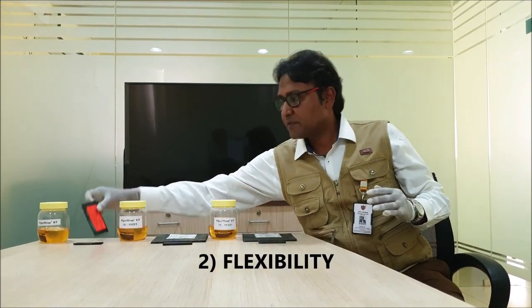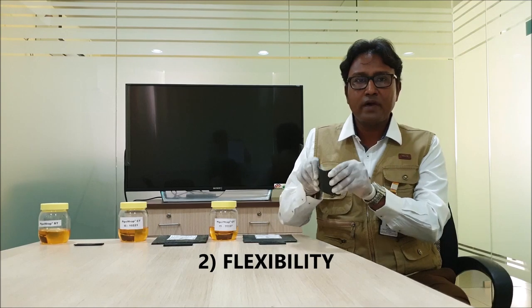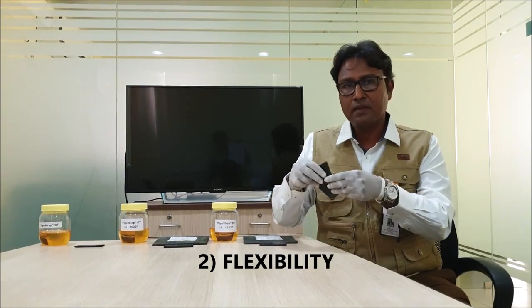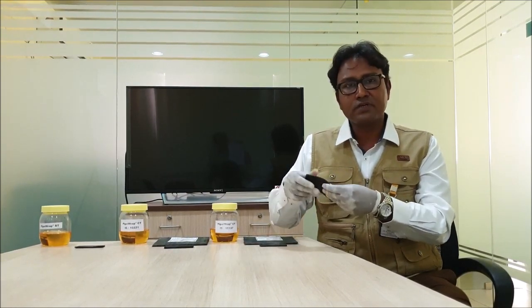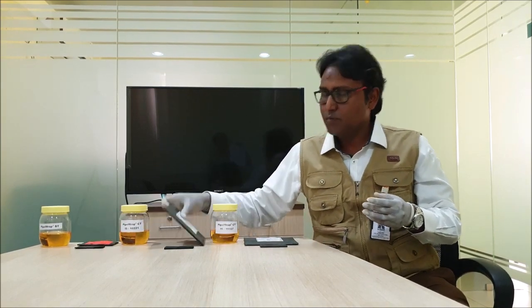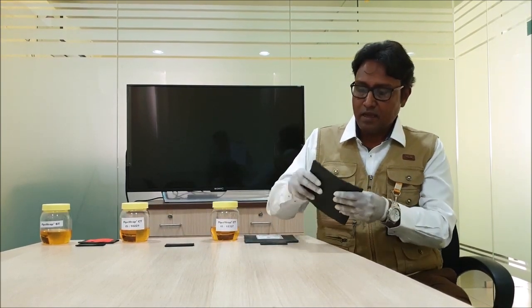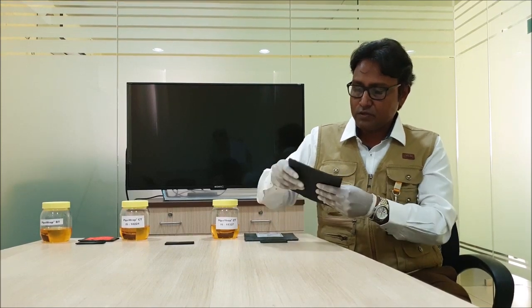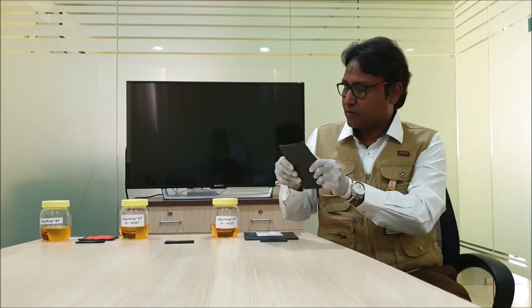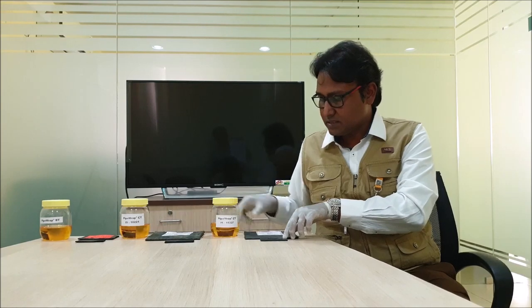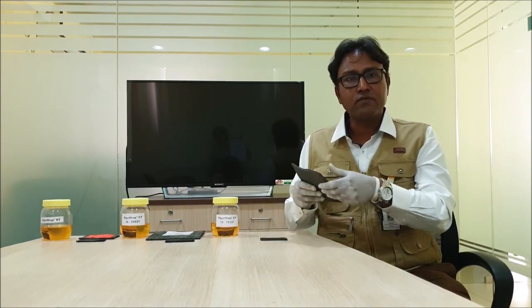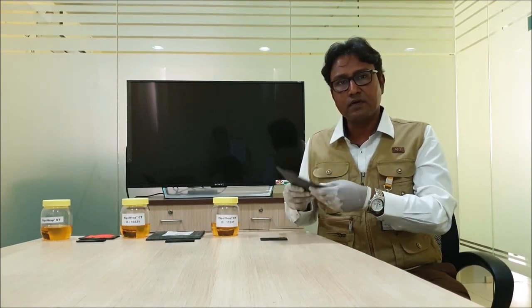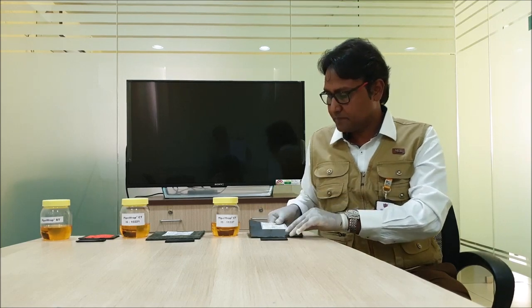A bituminous tape is usually quite flexible and easily pliable under all temperature conditions, whereas a coal tar tape is more brittle, and you can see that it is not so easy to twist it around. So this is a second difference with which we can differentiate between a coal tar and a bitumen tape.